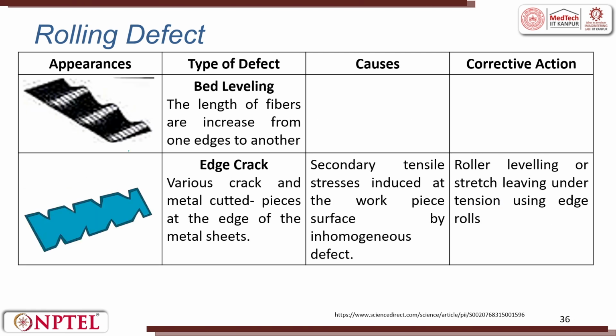In the appearance you will have this, these are bed leveling and these are edge cracking. Because there is not sufficient material, there will be tensile and compressive forces. So, you will get this edge cracking, right. The length of the fibers are increased from one edge to the other. So, it is almost like a taper also, you see it is a taper, bed leveling, and then edge cracking is this. So, these are the defects, these are the causes and these are the corrections which are made.